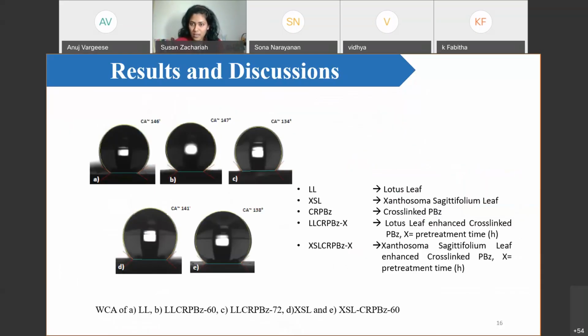After coating, the first test which we have done is the water contact angle. The water contact angle is a must-do test to find the hydrophobicity. If the water contact angle is high, it means it has more hydrophobic nature. Here I have given some of the names which I have used in my work. Picture A is the water contact angle of the lotus leaf, that is 146. The second one is after placing the PDMS and curing, which used a 60-hour pre-treatment. It gave the best water contact angle.